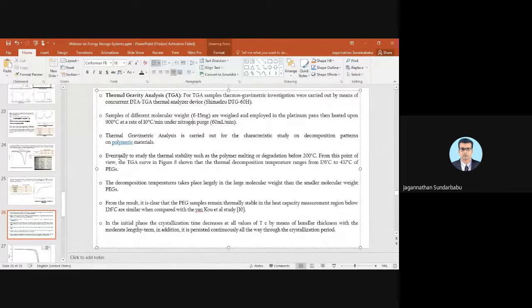The degradation process has also been carried out to find the thermal stability, right? To study the thermal stability, where the polymer melting or degradation should occur before 200 degrees Celsius, right? So from the TGA study, it has been shown that the thermal decomposition temperature of PEGs ranges from 176 degrees Celsius to 437 degrees Celsius, right? This is the range of thermal decomposition of PEGs, polyethylene glycols.